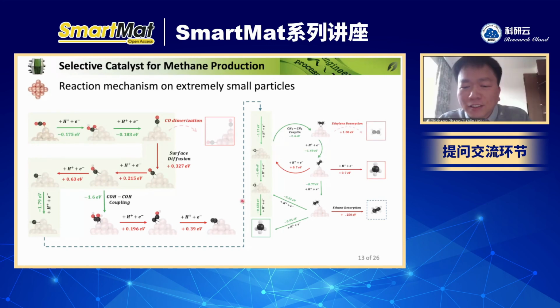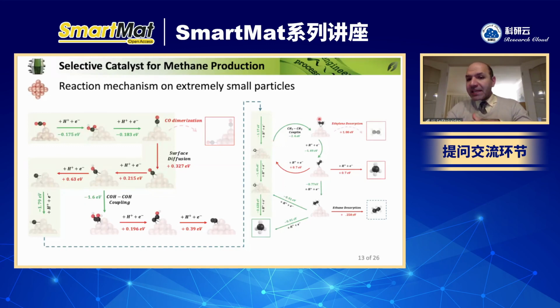So first of all, I need to clarify that no, not necessarily coupling happens and then decoupling. You can go from C to CH and then CH2, CH3, and then methane. So methane can also be produced through just a single carbon hydrogenation. So coupling is not the only pathway. But we say once you have CH2, you may go downhill to produce methane, but you can also have the coupling. It's possible. But then we say if the coupling happens, then eventually you have some sort of decoupling from ethane to produce again methyl adsorbed on the surface, and methane desorbs and goes to the gas phase. So this is just clarification.